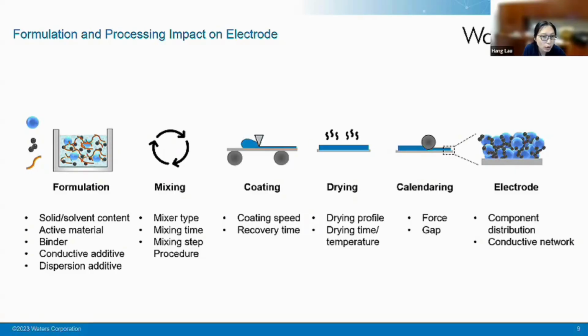And then coating speed. One of the big things I will talk about a little later is that when you coat, the slurry is actually under high shearing. Oftentimes the structure breaks down, and that's a process called recovery. I will talk in a little more detail about how the recovery time will have a big impact on your slurry formula and post-manufacturing. And drying: you need to make sure of your drying profile, drying time, and temperature.